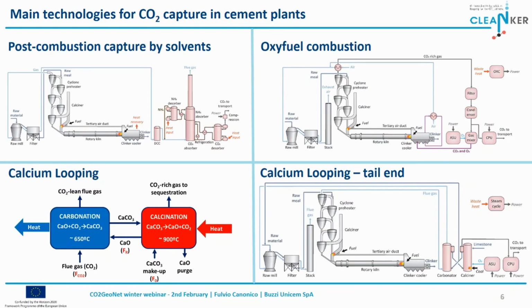Another very interesting solution is the so-called calcium looping. Calcium looping is a way to capture CO2 by using calcium oxide. Calcium oxide is able to react with CO2, forming calcium carbonate at 650 degrees. And if you are able to calcine the calcium carbonate in oxygen in another reactor, then you will be able to obtain free calcium oxide that could be used again to capture CO2. So this is the basic concept. This is basically a looping of calcium. The calcium is used to react with CO2 and then is calcined in an oxygen environment, in an oxygen reactor.